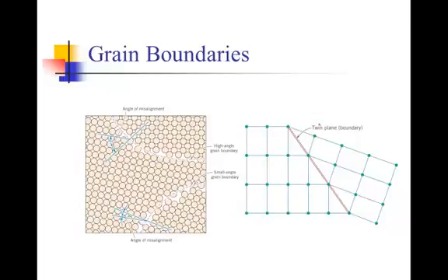The last type of aspect of grain boundaries that I want to talk to you about is when you have a grain boundary that acts as a mirror image of the crystal. So along this twin plane here, the different crystals on either side of that twin plane look like mirror images of each other. And that typically happens when you have a crystal that has a mechanical force applied to it while it's hot, and the force was not applied during the original growth of the crystal, and then the crystal can twin to relieve that mechanical force.